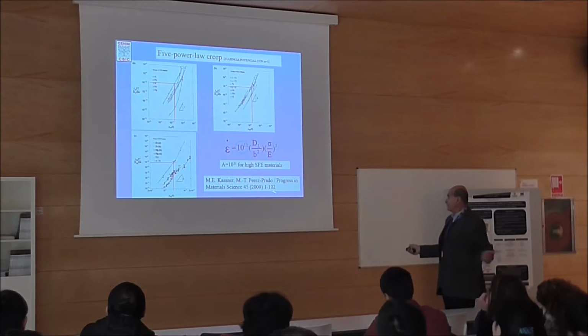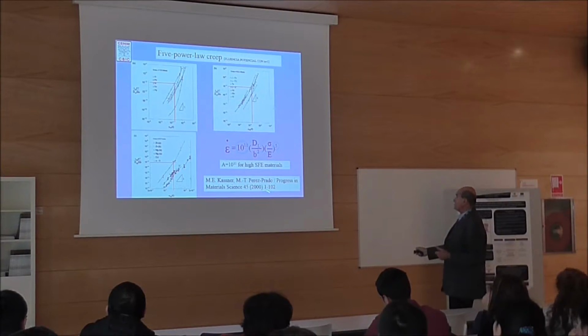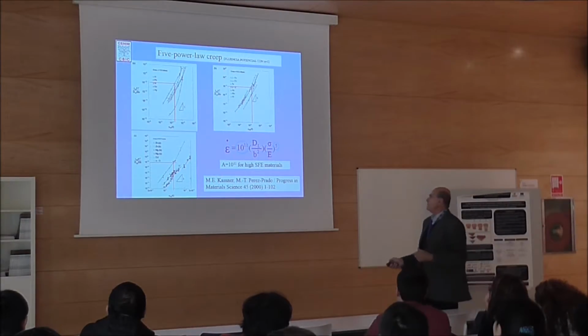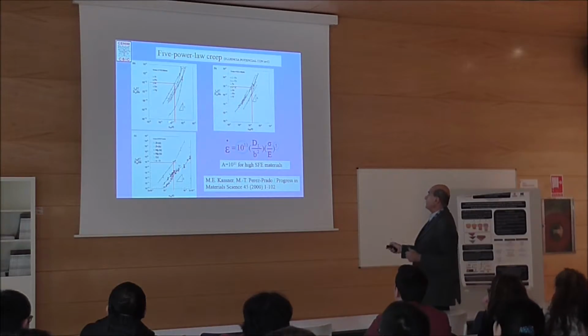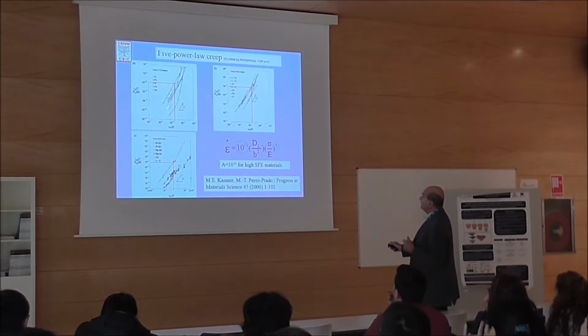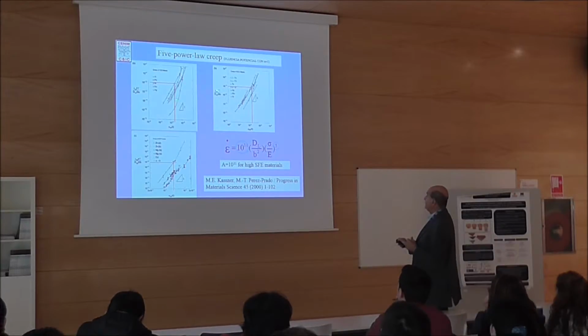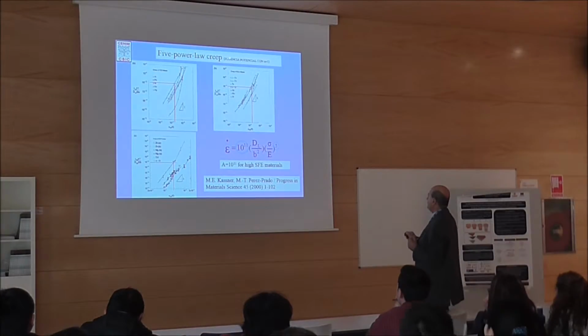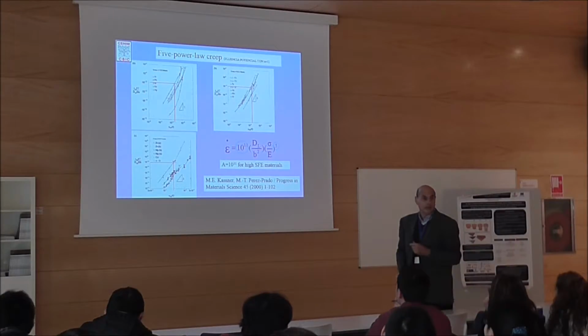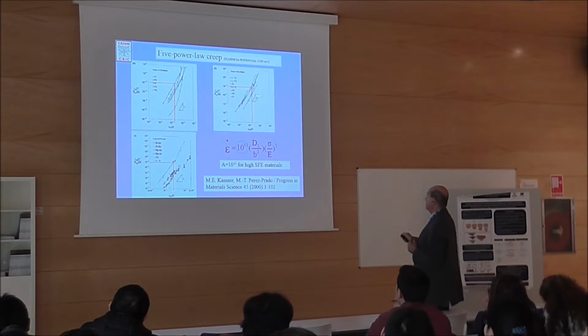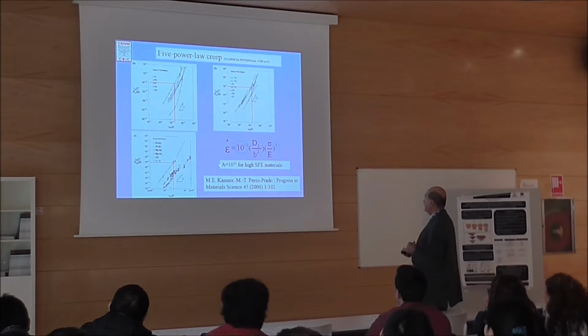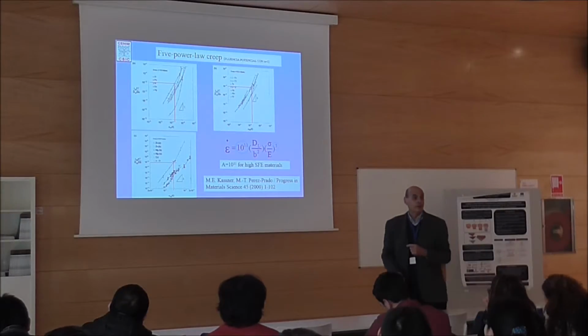You can go to Kassner and Perez-Prado, they published a very nice summary in Progress in Materials Science 2000, where you have a lot of information. One piece of this information is that for all types of materials, FCC, BCC, HCP, the stress exponent is about n=5 for many materials. And if you calculate the pre-exponential constant A, it is 10 to the 11 for high stacking fault energy materials.